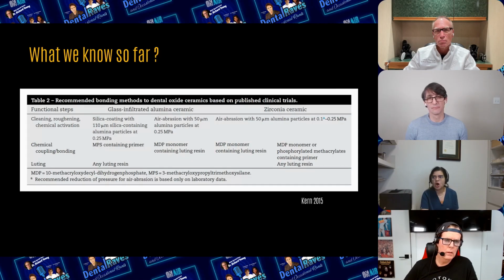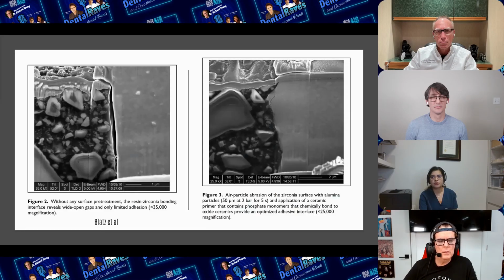So, a recommendation based on these published clinical trials. We also discuss the in vitro side of it. We know air abrasion with 50 micron alumina particles at 0.1 to 0.25 MPa pressure creates a good surface for bonding, and then an MDP or 10-MDP containing monomer or a ceramic primer will give you the chemical coupling for bonding to a zirconia surface. And then you can use any luting resin cement to create that adhesion between the zirconia restoration and the tooth. This again is from the Blatz paper in 2018.